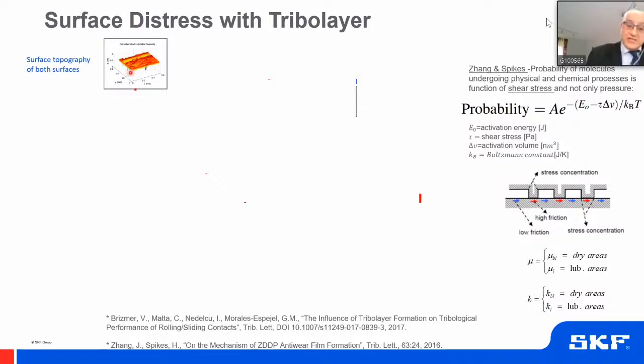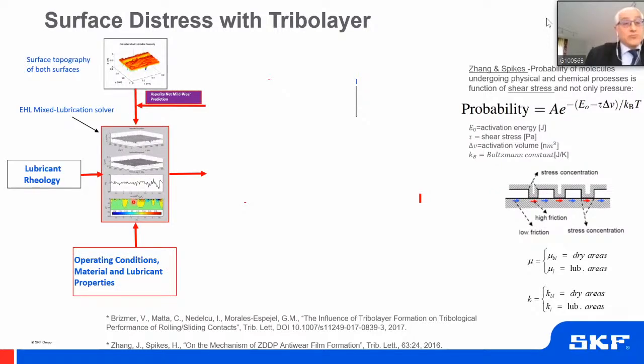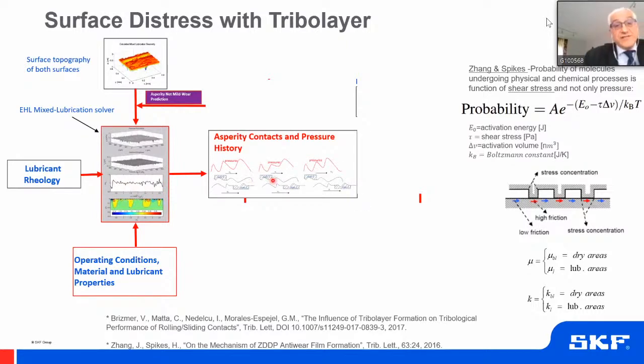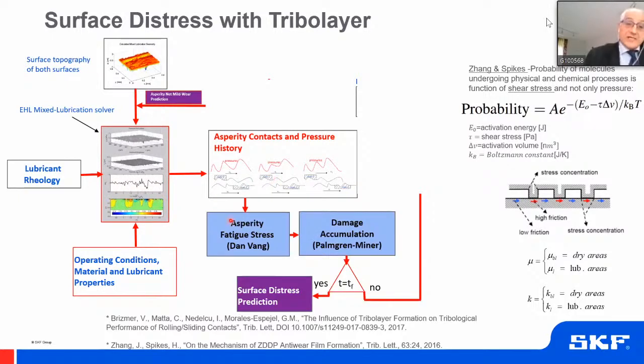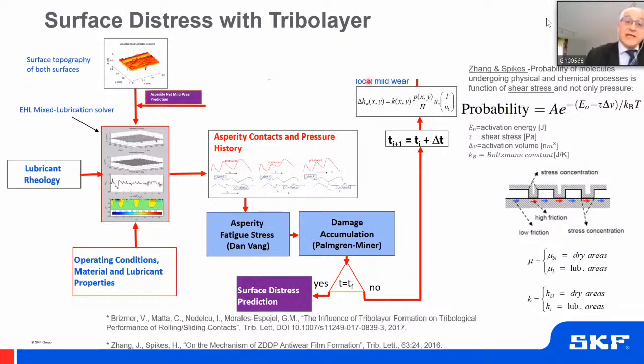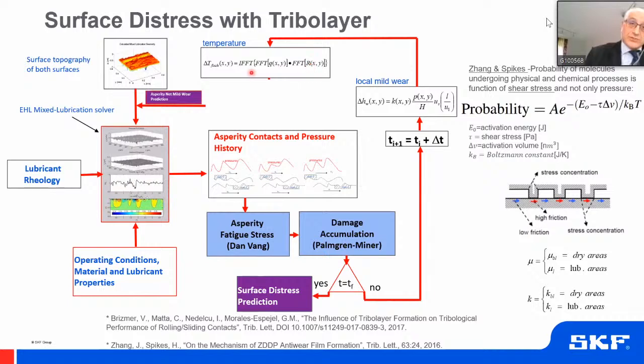So you basically measure the tribofilm, you measure the topographies. We introduce these topographies into the mixed lubrication model, the fast mixed lubrication model, together with the lubricant rheology, the operating conditions, the material. We are able to calculate the stresses and eventually the stress history of the roughness going through the contact. With that, we go to a fatigue criterion to assess the damage locally and eventually to accumulate this damage over time. If we have reached the number of load cycles, we report the results. If not, we increase the time. We apply a local wear model. We calculate the local temperatures, and eventually we calculate the local increase of tribofilm. And then we repeat this process many times until we reach the simulation time.